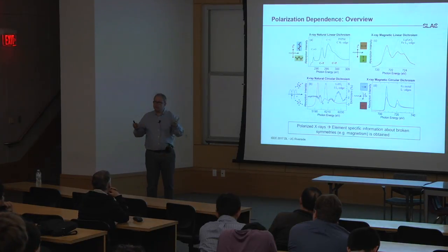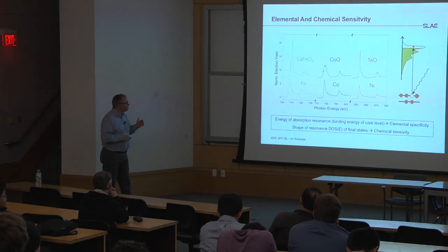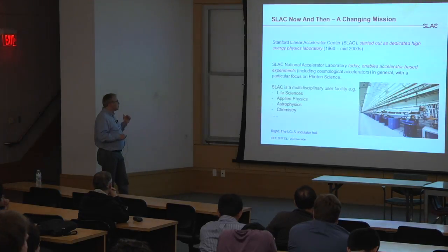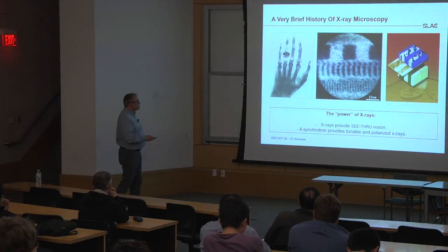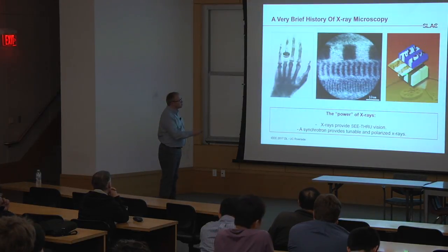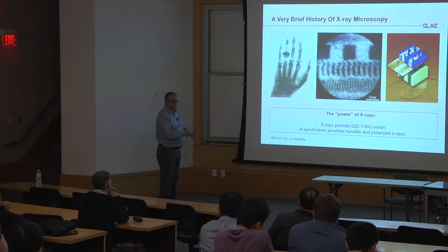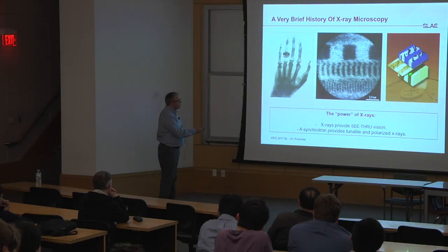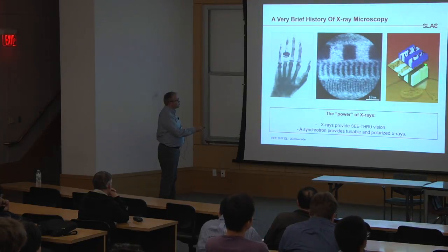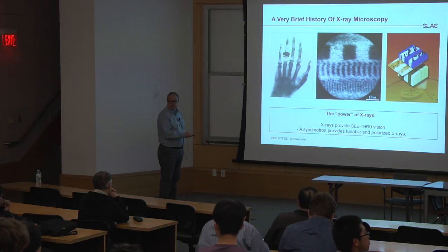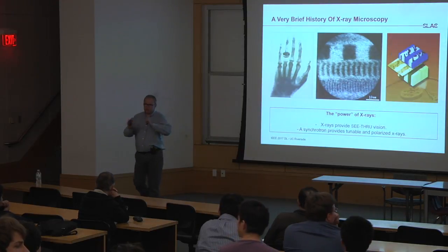But if you want to measure antiferromagnetic domains, for example, in this case, these are domain images of ferromagnetic cobalt on antiferromagnetic nickel oxide. The illustrator put it a little bit together. These are domains where the cobalt would be either pointing up or down, and the antiferromagnet axis is like this. While here, the cobalt spins point left and right, and the antiferromagnet axis is like this. So you can then correlate antiferromagnet and ferromagnet together.